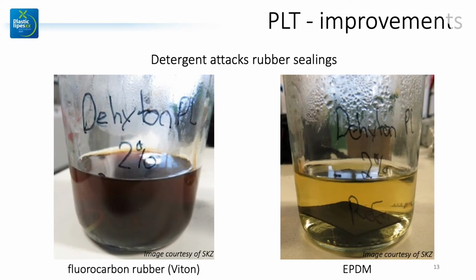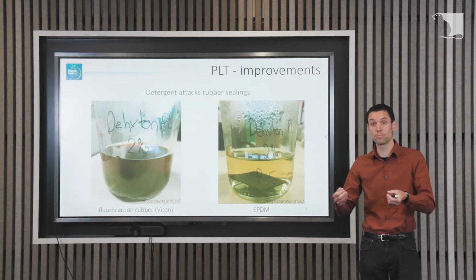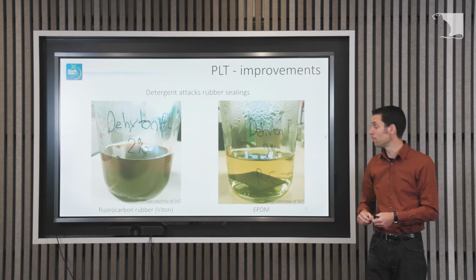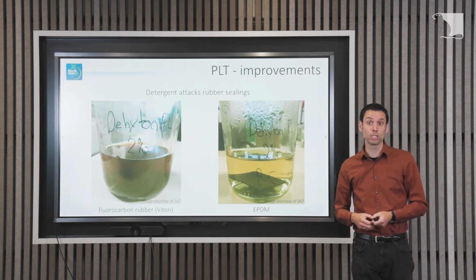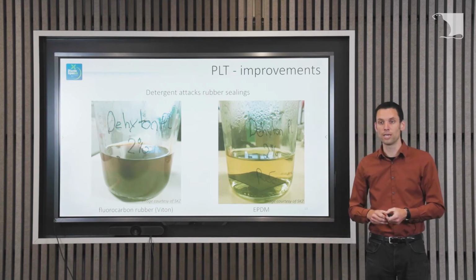Now, what was the first problem, for instance, is the detergent. The detergent we were using in the beginning was detergent at 90 degrees. So what did the detergent do? It attacked all our rubber connections. So we have all the rubber, like Viton, for instance, and these are pictures by SKZ, and Viton rubber is attacked very strongly by detergent at 90 degrees. So all our quick fix connections started leaking. Everywhere where rubber is used, also the circulation pumps, for instance, they're using rubber, we have to replace them. So for instance, the quick fix we replaced by simple screw connections, but the rubbers in the pumps, we replaced them by EPDM, which have had a much better result and were much more resistant to detergent.